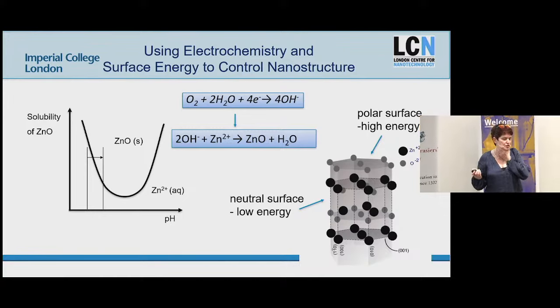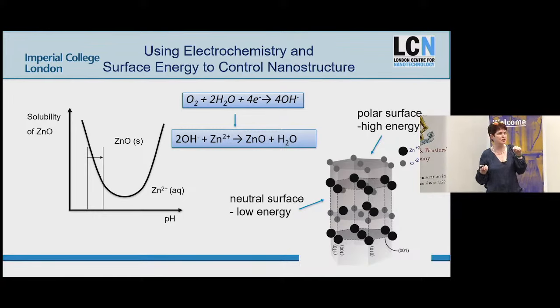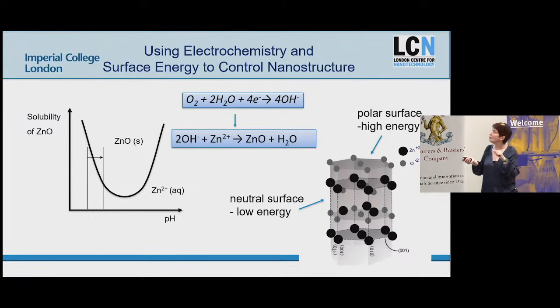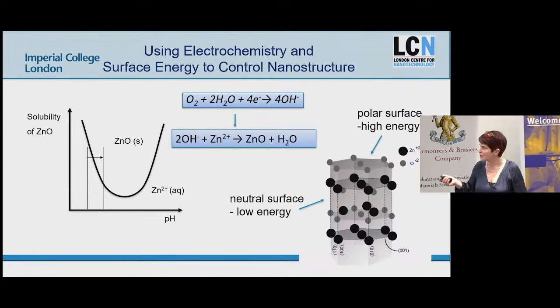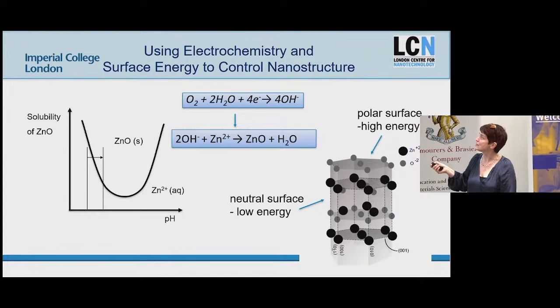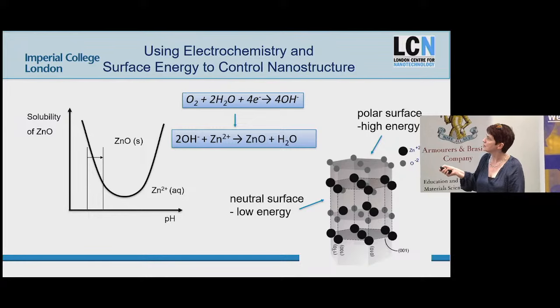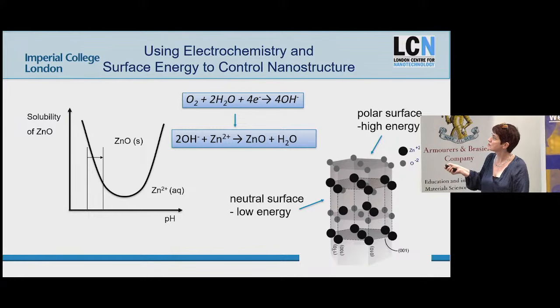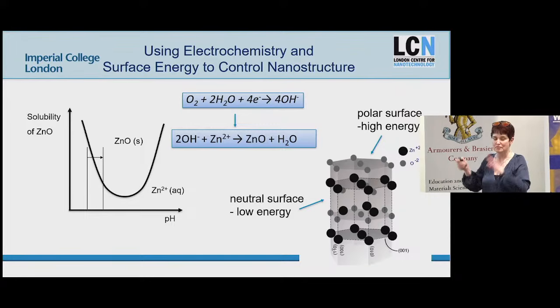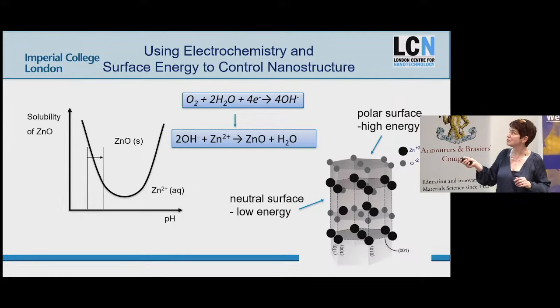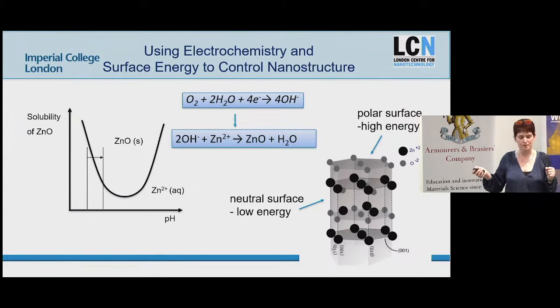So I'm going to start by just talking about that surface energy factor and how you can use surface energy to make interesting structures. This is what we would call a very, very simple phase diagram. What this shows you is the solubility of zinc oxide as a solid versus zinc 2 plus as an ion. If we are in this region for pH, you will find zinc 2 plus will dissolve. So zinc oxide will dissolve at high and low pH. That's essentially the message. If you can control your system in here, you've got zinc oxide solid.